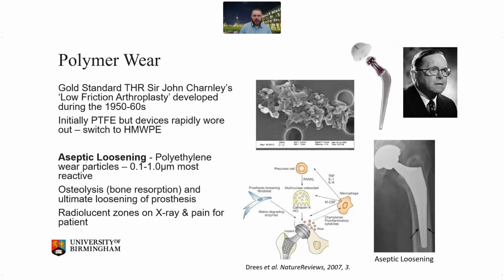But ultimately, these components wore out way too rapidly, so there was a switch to high molecular weight polyethylene. Ultimately, though, wear became the main focus, or the limiting factor, for hip replacements. The wear debris, or the polymer particles released from these joints, as you can see in the image here, would agglomerate and be released in a very specific bioactive range. So they were submicron, less than 1 micrometer in size, and they would go on to elicit an immune